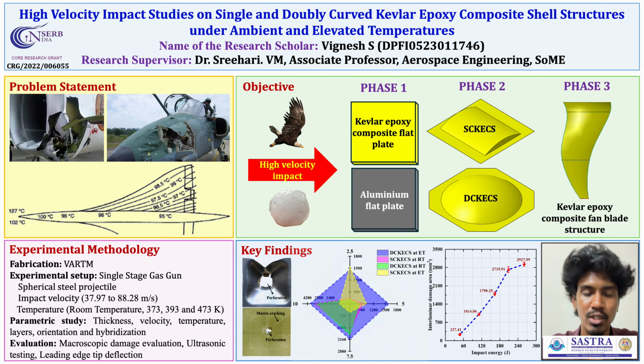The fabrication was done using the VARTM method, vacuum assisted resin transfer method, and impacted using a single stage gas gun facility with a spherical steel projectile. The impact velocity was between 37.97 meter per second and 88.27 meter per second, and impacts were done at both ambient and elevated temperatures of 373 Kelvin, 393 Kelvin and 473 Kelvin. We also investigated the effect of thickness, velocity, temperature, and the effect of orientation and hybridization of carbon and Kevlar fiber.